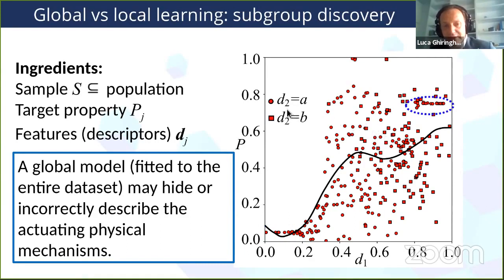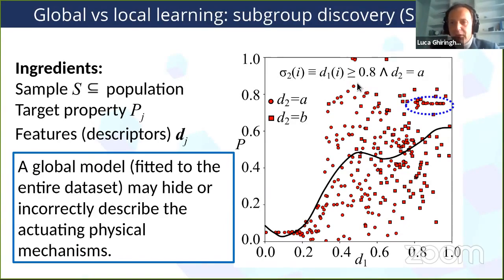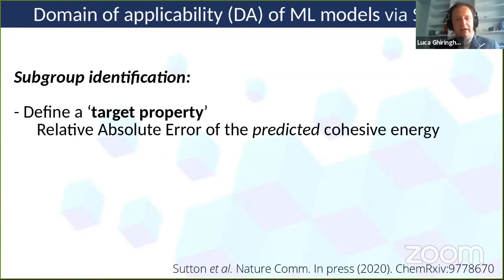Further, you may also use another feature that here is symbolized by two different symbols on the plot, squares and circles. Then you may notice that if you focus on the circles and the value of the feature D1 is bigger than a certain threshold, you also have a good fit with a horizontal line. So now imagine that you have tens, hundreds of these features, and you want to search all the combinations of these features in order to find subsets that have a simpler model than the global model, or some outstanding characteristic of the properties of the data points with respect to the other models. Of course, you would not like to do that manually by browsing all the pairs or the triplets and so on. You want to have an automatic method to do that. And this is what we are doing now with subgroup discovery.